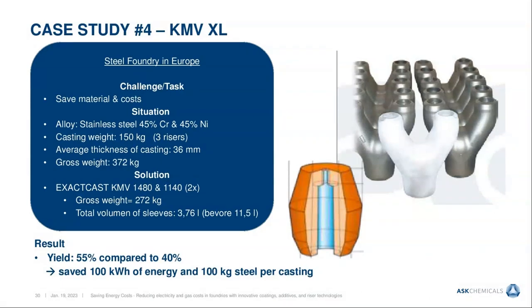Here we have again one steel casting. In this case it was a stainless steel part with an alloy with chromium and nickel. And the gross weight of this casting was 370 kilograms. And applying the solution from the KMV XL risers, we were able to reduce the gross weight of this casting to 272 kilograms, and the yield of this casting improved from 40% to 55%. And the foundry was able to save around 100 kilowatt-hours of energy per casting.